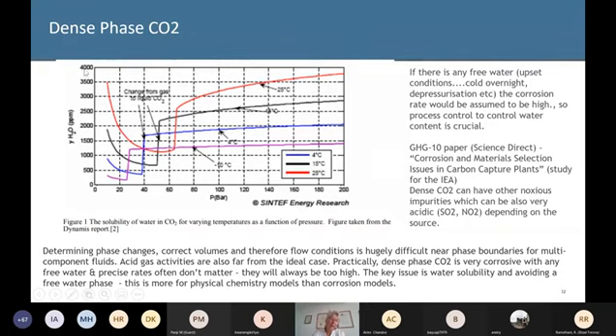What we've got here is the water content. So the thing is that the liquid CO2 can actually dissolve a larger amount of water than the gaseous phase can carry. So if you have dense phase CO2, your major focus is on whether there are upset conditions that could lead to the dense phase generating some gas, because that will drop out water, and that water will be supersaturated with CO2 and very corrosive.